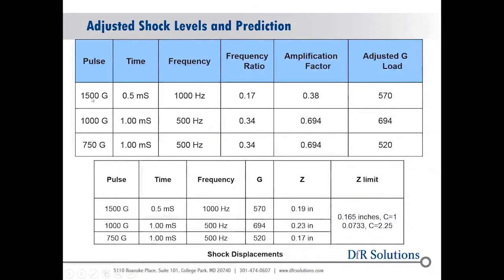So here are the modified values. For that example, we have 3 G levels with 2 different time pulses, their effective frequency, and then what the effective adjusted G load is. You can see the most damaging level here is the 1000 G, 1 millisecond pulse, even though we have 1500 Gs here. It's just that the frequency of the pulse is fairly far away from the circuit board's, so it's just not doing as much as the 1000 G pulse.